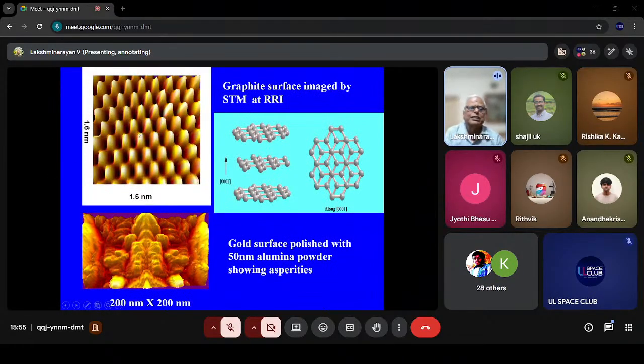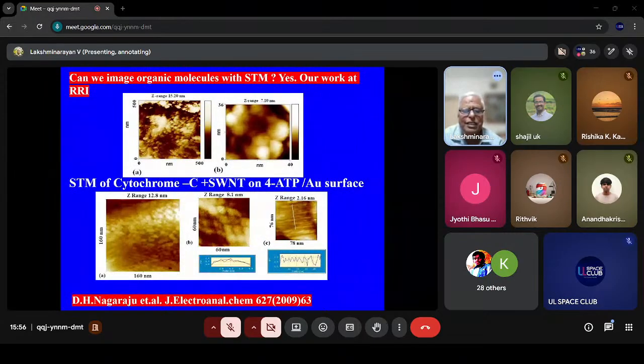And subsequently we could get spectacular images. So this is one of the three-dimensional images of graphite, and this is the gold surface polished with 50 nanometer alumina. You can see these are alumina surface. If you polish it, you can actually see the gold surface as a mirror. But if you really scan it with STM, you find there is so much roughness here. You can see that there are so many depressions and asperities, hills and valleys. So this is a mirror image, actually. The mirror image confirms that whatever you are seeing in the forward scan is reproduced.